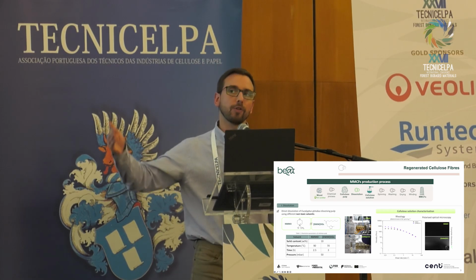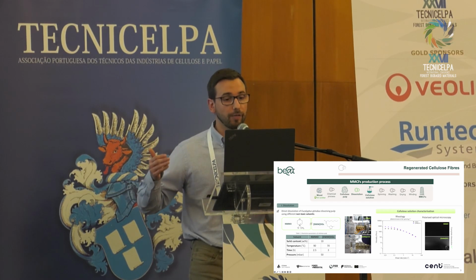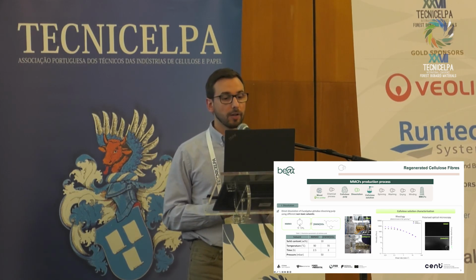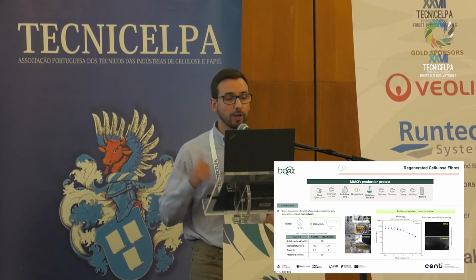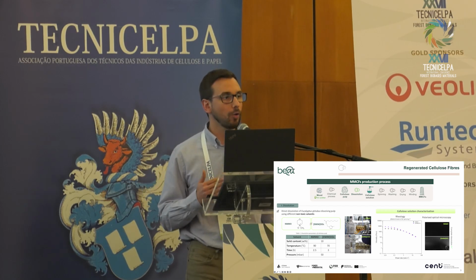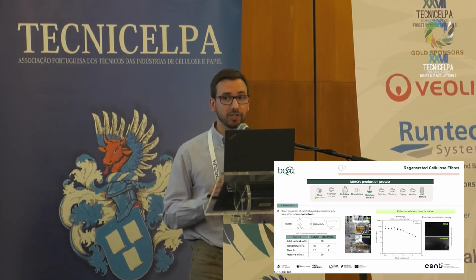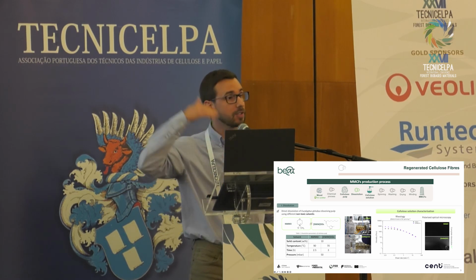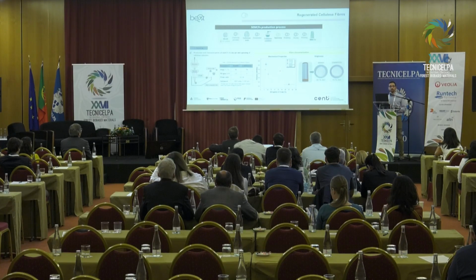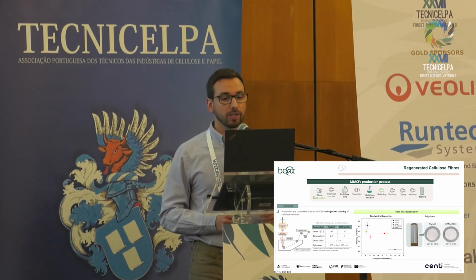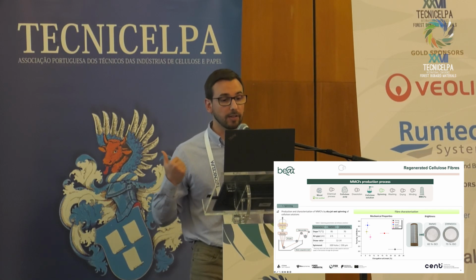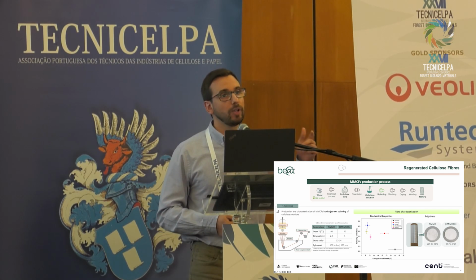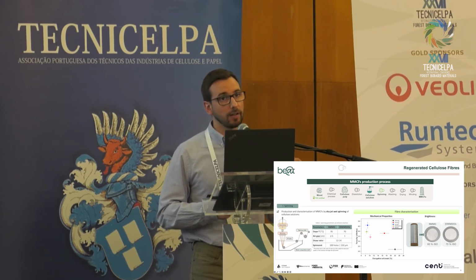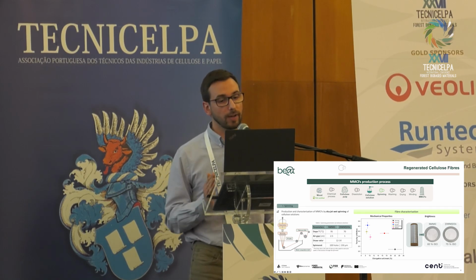And what we saw was that, in order to achieve complete dissolution and a solution of 10% concentration of cellulose, we spent roughly the same time for dissolution, but we achieved that using a substantially lower temperature when we use the ionic liquid. And this is very interesting in terms of energy consumption when we think about scaling up, right? So then we took these solutions and spun them into fibers in also a pilot scale spinning unit and under the same parameters. And what we saw was that we got fibers in the end that had higher tenacity when we used the ionic liquid in comparison with the conventional lyocell fibers, although elongation was a bit lower.